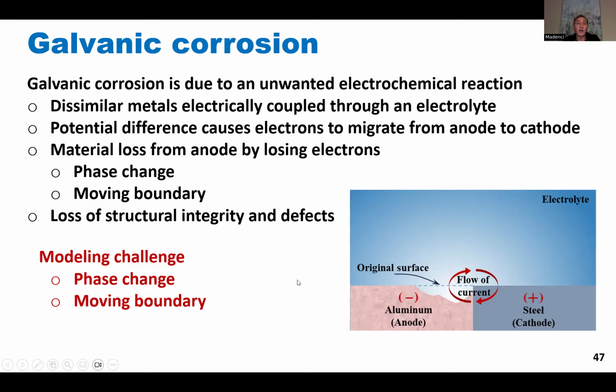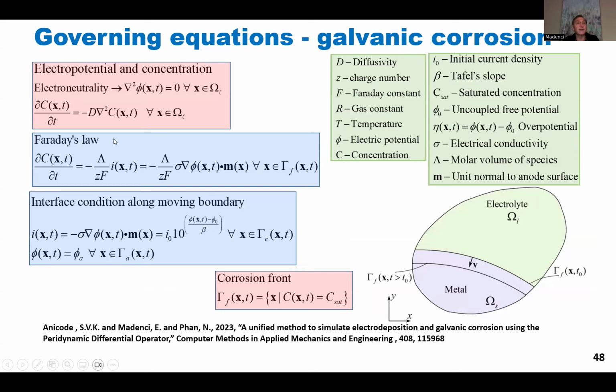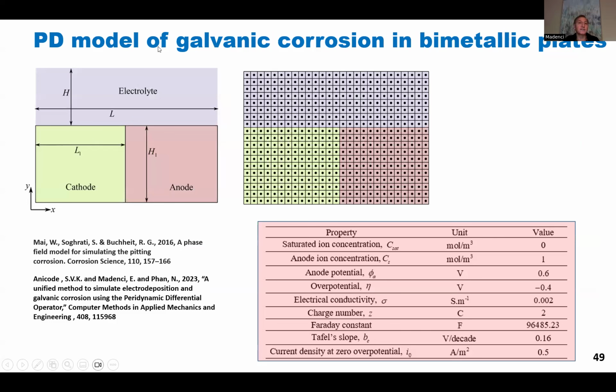So how do we model this? It's a challenging problem. For governing equations, we have the electropotential and concentration. These are solved in a coupled way, and there are pretty well established interface conditions along the moving boundaries, and so we monitor the corrosion frontier. As I mentioned before, the peridynamic bond has a status parameter. You can either kill it or give birth to it. In this case, the peridynamic bond changes phase. It becomes electrolyte, basically representing the electrolyte here. So here I have the discretization.